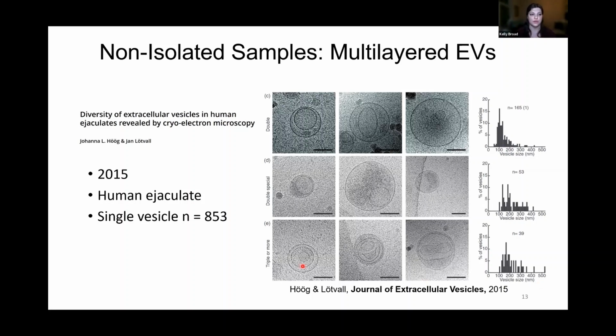For a sense of numbers, they identified 853 single vesicles, 165 double vesicles. They categorized those electron-dense vesicles with a smaller vesicle within them as double special vesicles and found 53 of them in the sample, and 39 EVs that were triple or more layers.